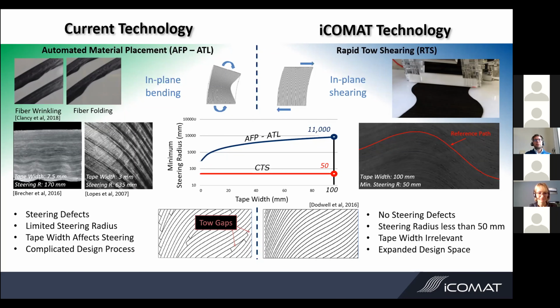And there's really a limitation on the width of the tapes that you can use with AFP and ATL. And the wider the tape, the harder it becomes to steer. So this is where the concept of minimum steering radius comes from. And that's traditionally around 500 millimeters to a meter for AFP. And that's the minimum radius that can be steered without defects. And as the tape width increases, that minimum steering radius increases as well.